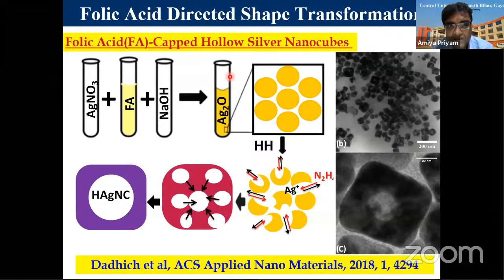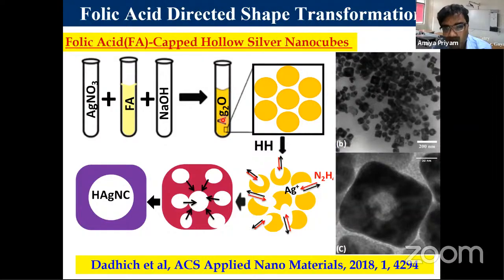In the previous case, we used citric acid as the capping agent. Here, using folic acid, I can also tell you that the 4 parameters that I told you about are affected by temperature very much, all of them. So it is very crucial to optimize the temperature. In the previous case, when we were using citrate, the temperature was around 20 degrees C, where we get optimum peak positions, like red shifted and narrow peaks. In this case, because folic acid molecules are slightly larger, they move slowly. We had to heat it up to 50 degrees, slightly higher than room temperature. And then we found that we are getting the hollow structures.